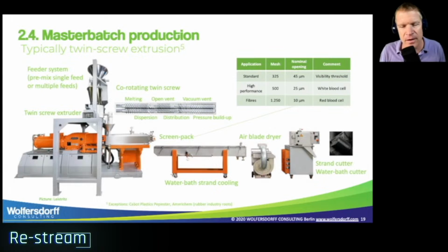After the screen pack, we might go into a water bath strand cooling, and then the plastic is cooled and solidified, but we need to dry the water off. We might have an air blade dryer, and then we need to cut the strand into little pellets, cylinder-shaped pellets, or if you have a water bath cutter, also underwater cutter, we have more pellets that are more shaped like lentils.